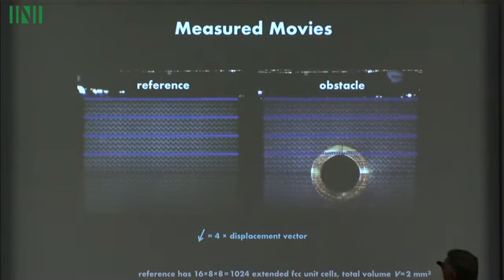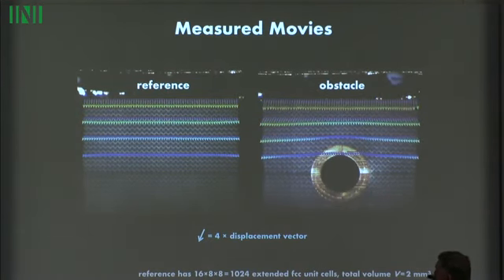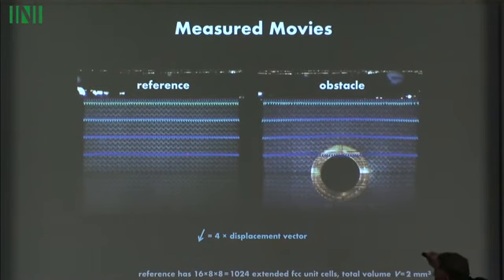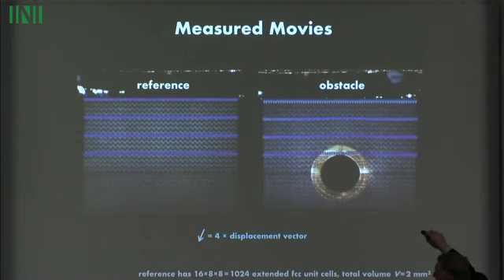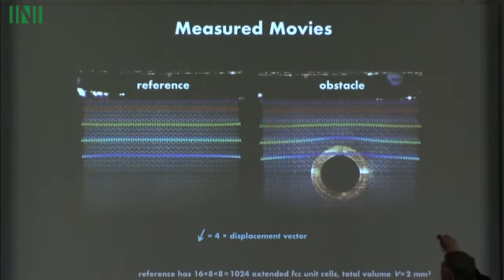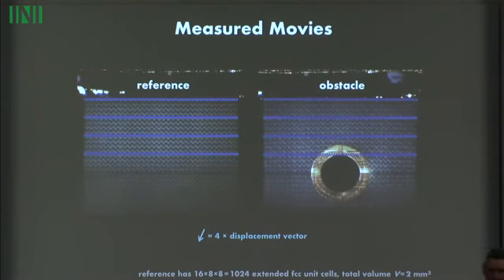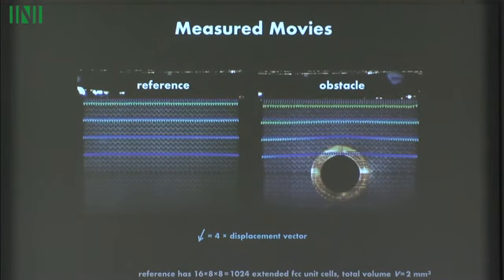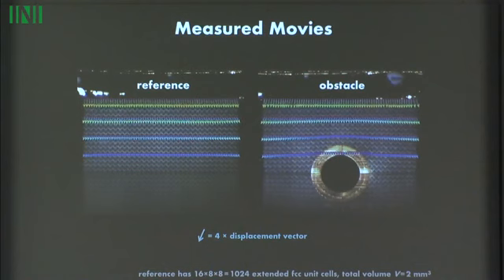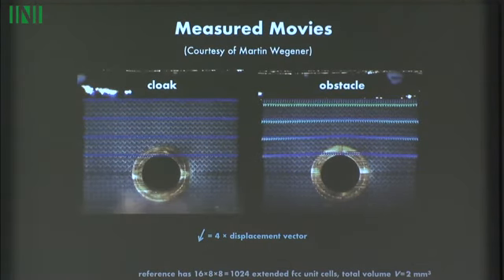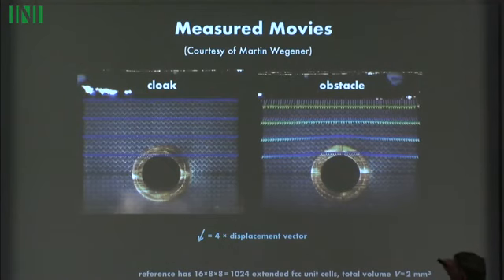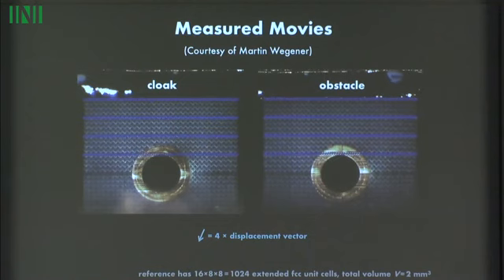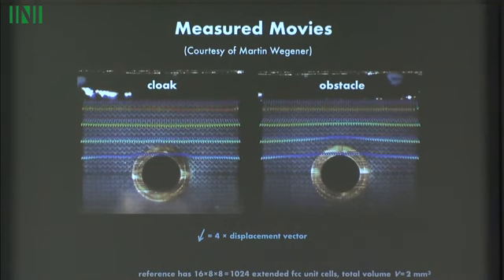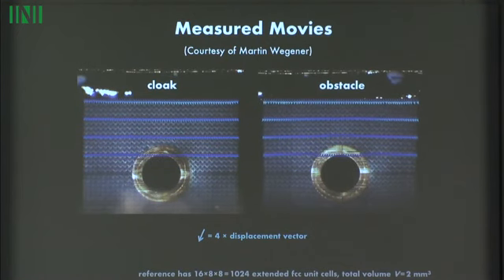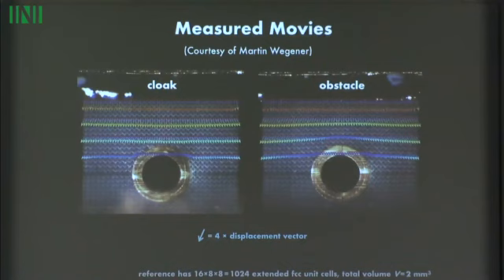This is just a reference, a pentamode structure without any cloak. Here is the obstacle, and it's being loaded vertically from above, and you can see these lines are deformed by the obstacle. Yeah, so this is with the cloak, and with the cloak present, the lines remain almost horizontal here, so it does a good job of shielding what's underneath it.